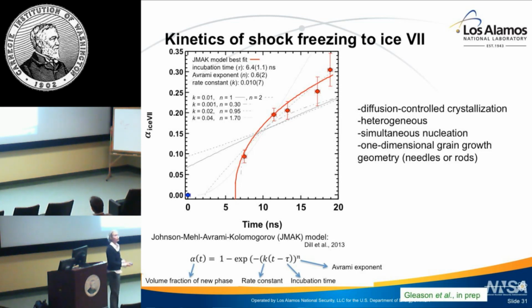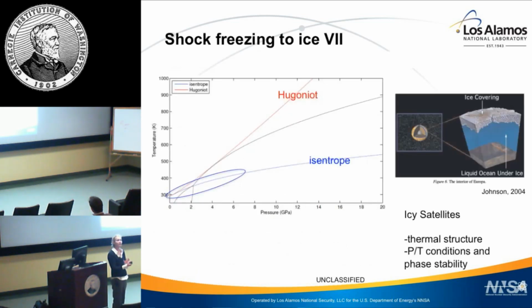We have the opportunity now to use these methods developed in classical nucleation theory and apply them to time-resolved, high-pressure, high-temperature shock compression data. So perhaps we can think about this in the context of icy satellites or icy planets, in learning about their thermal structure and pressure-temperature stability regions. Again, I point out we're really only looking at very low pressure here, maybe up to 5 to 7 GPa. So we're focusing more on icy satellites than any high-pressure opportunities, certainly not superionic and the like. But this could provide some constraints.